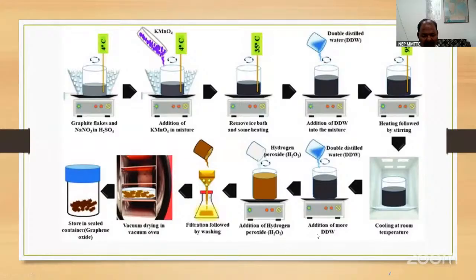Cooling at room temperature, then the addition of more double distilled water, addition of hydrogen peroxide, that is H2O2, then the filtration, vacuum drying, and then store in a sealed container, that is the graphene oxide. So this is it here.